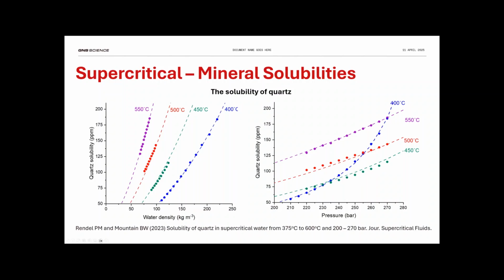And we can see as we approach the critical point, so we're getting close to the critical point at 400, the solubilities start to go up, and at the critical point, the solubilities go up almost exponentially to infinity.